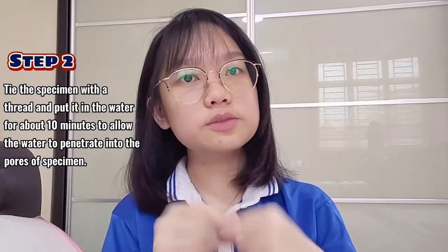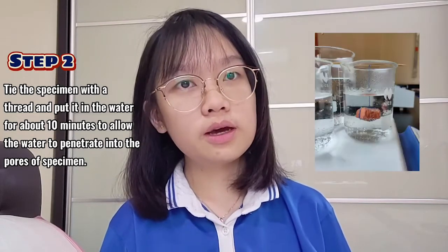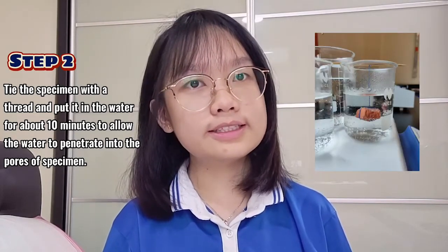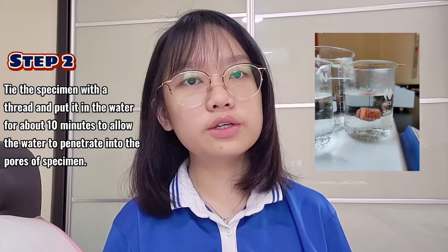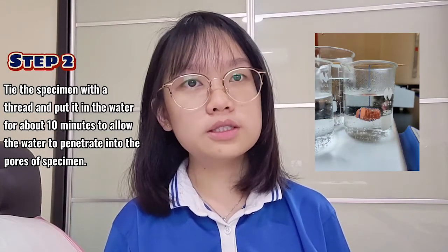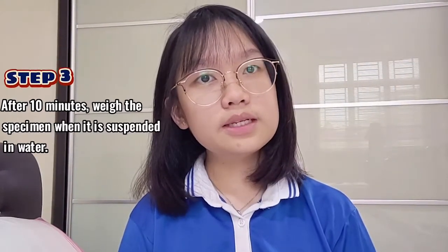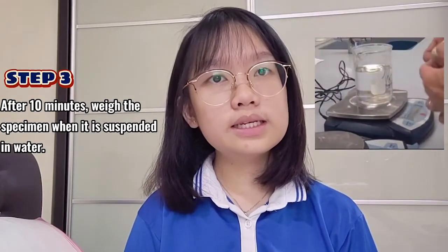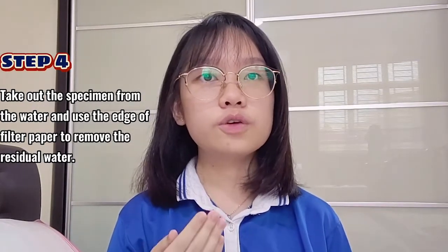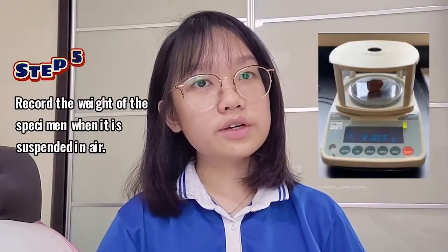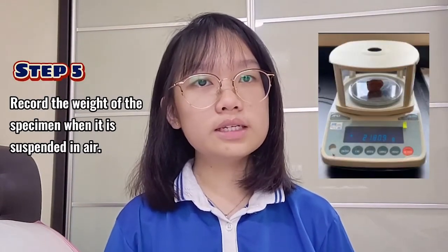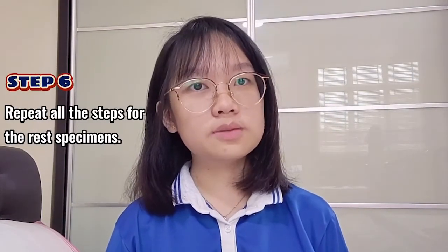Then tie the specimen with a thread and put it in the boiling water for about 10 minutes to allow the water to penetrate into the pores of the specimen. After 10 minutes, weigh the specimen when it is suspended in water. Then take out the specimen from the water and use the edge of filter paper to remove the residual water. After that, record the weight of the specimen when it is suspended in air. Repeat all the steps for the rest of the specimens.